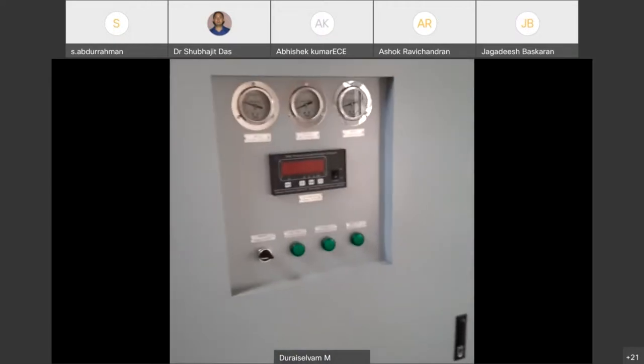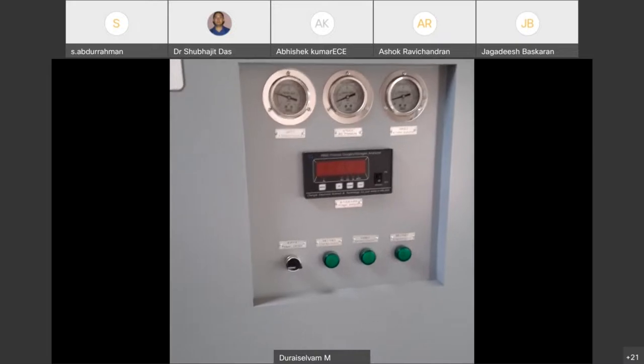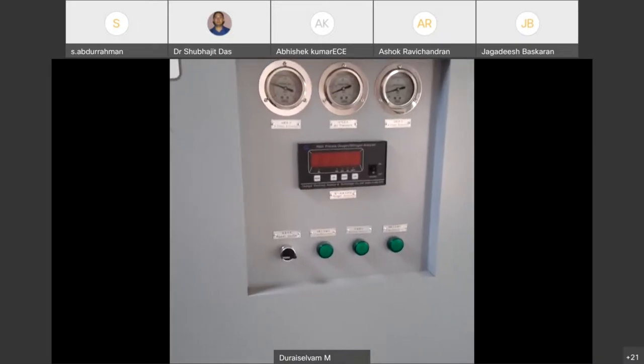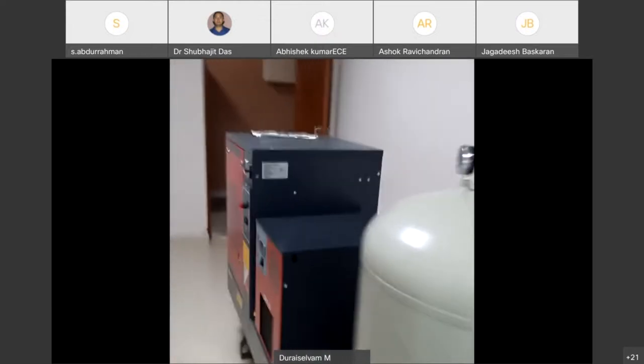Only when the nitrogen output is 99.99%, we should start the build process, to ensure that the build is taking place in an inert atmosphere as much as possible. During additive manufacturing processes, we either use argon or nitrogen. Ampro recommends a nitrogen generator for all the builds. So with Ampro, this is a commercial printer. Titanium 6Al4V, stainless steel 316L, Inconel 625 and 718, and cobalt chromium molybdenum parts can be printed if powders are available.